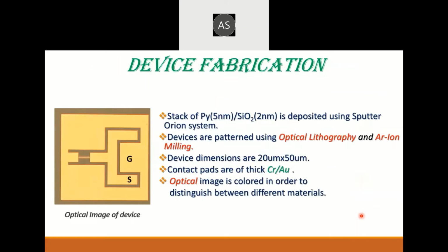Now, coming to the device fabrication, it's very simple fabrication after optimization. What we did with the Sputter Orion system, because lithographically we did not find any kind of challenge, as this graphene is now being protected by permalloy and a capping layer of silicon dioxide. So we have used simply optical lithography for patterning this device, the strips, that is 20 micron by 50 micron, and simply a gold contact on top of it.